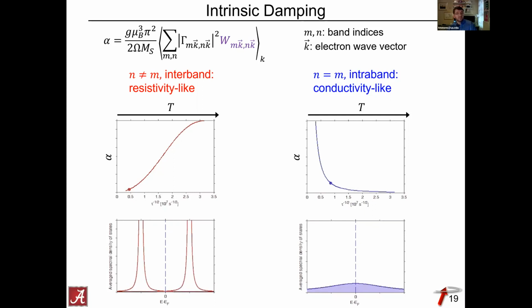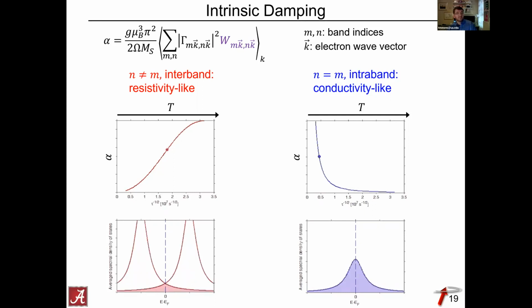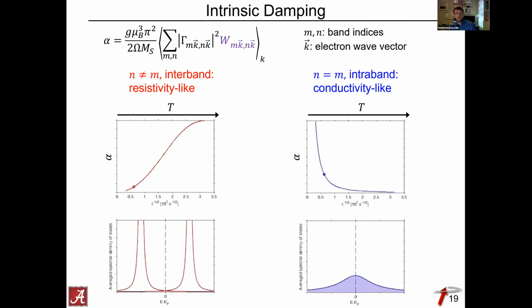The way this works is, as you lower the temperature, in this animation you see that the overlap of these two bands at the Fermi energy actually diminishes. Therefore, what you expect for this contribution is that it decreases as you decrease the temperature. This is very different if you look at an intraband term, where essentially you create electron-hole pairs in the same band.